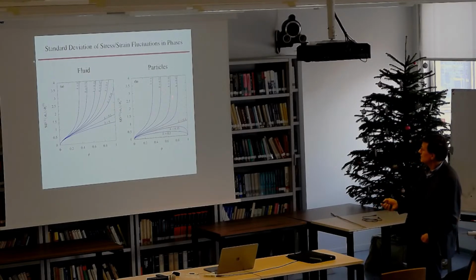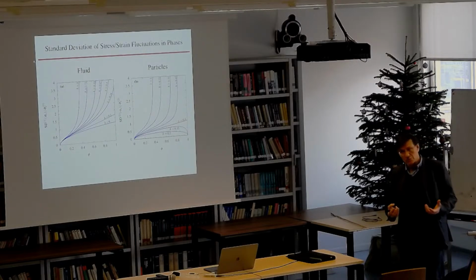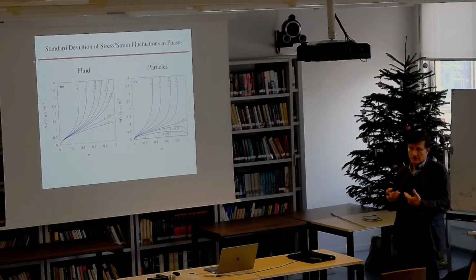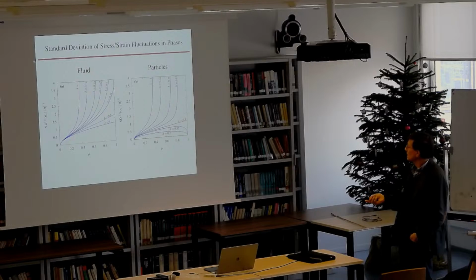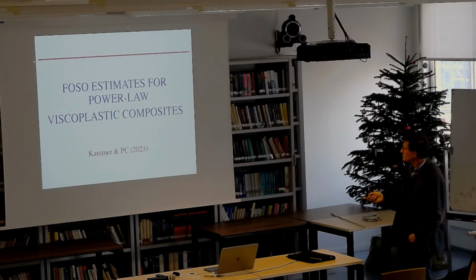On the other hand, in the particles, you also need to have strong fluctuations, because of course you have to satisfy the conditions of equilibrium and compatibility across the boundaries. So you get this additional information which could be useful for mechanical systems. It could be okay.